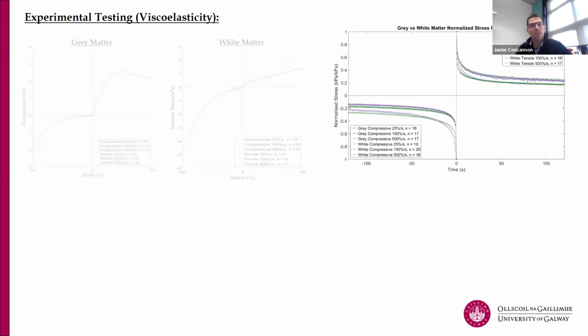We then took another batch of samples and we tensioned them to 50% and we compressed them to 50%, and we held that strain of 50% for over 2 minutes, and we looked at the stress relaxation, which is another hallmark of viscoelasticity. And again, we're seeing here that there's no statistical significance in the gray matter recovery of the stress, the stress relaxation, but there is again a statistical significance in the white. So the gray matter is almost like it doesn't matter what speed you load it at, it behaves the same, but the white matter then behaves very, very differently in these different configurations.